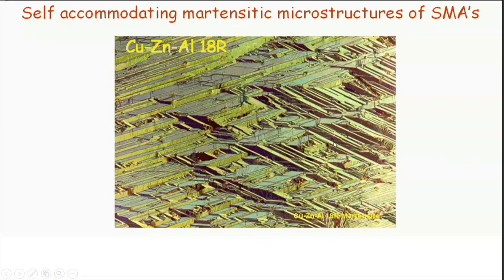In addition, there's something I'll make a mention of, though there is nothing supporting it that I can see here, and we'll mention it again in the slides to come: these interfaces are very typical, and they are also glissile. They're very easy to move around. And it so turns out they're also twin interfaces. Most of them are twin interfaces, and they're very easy to move around. So unlike other martensitic microstructures, this is entirely different in the case of shape memory.